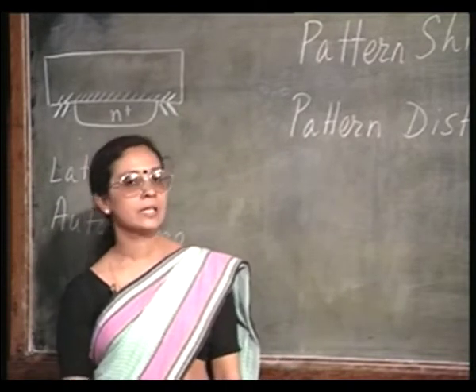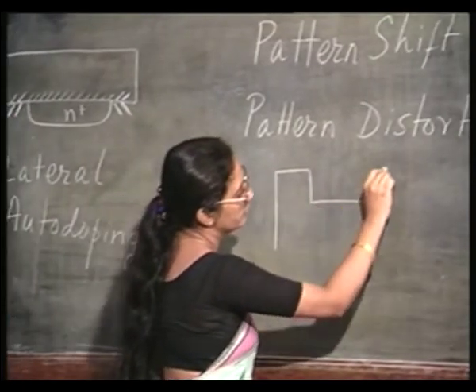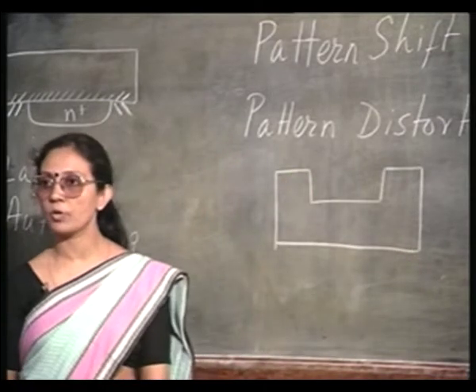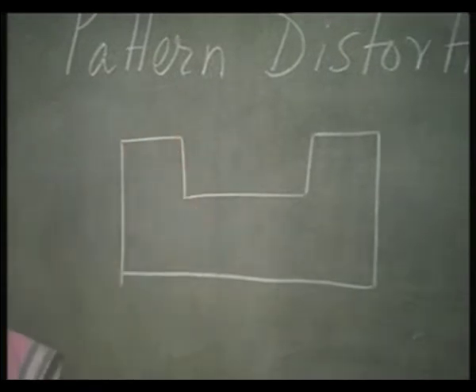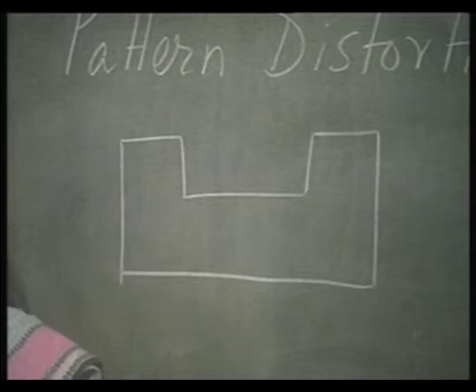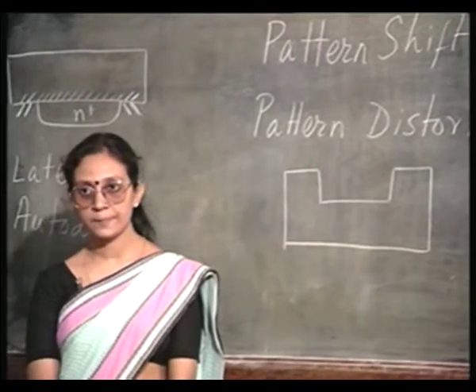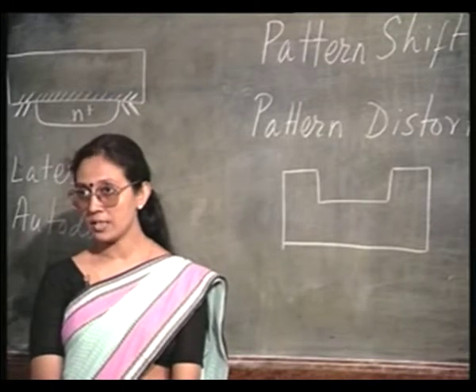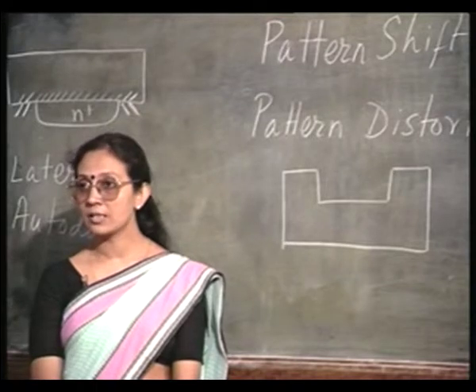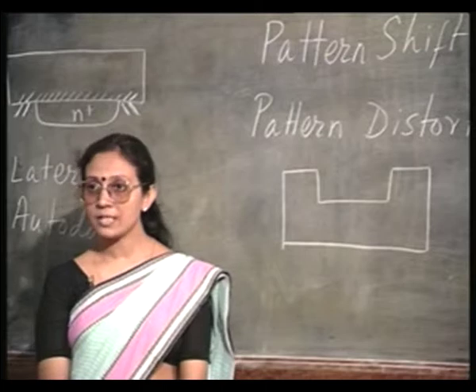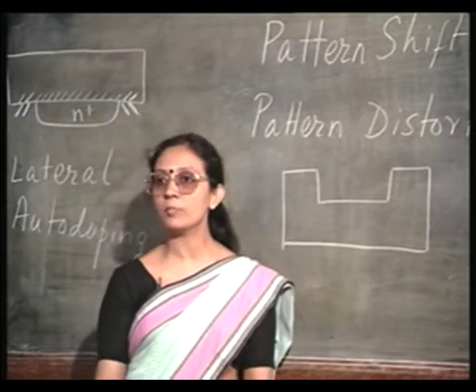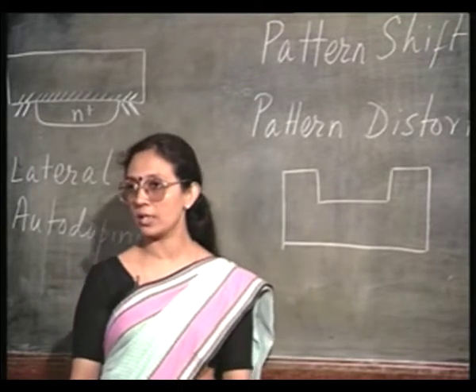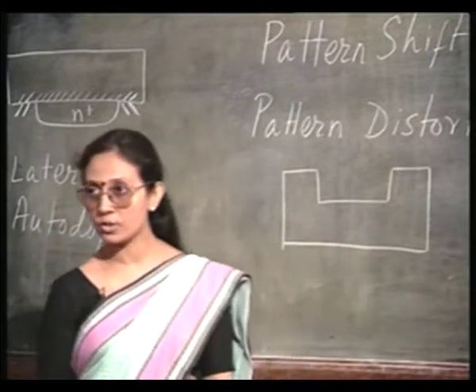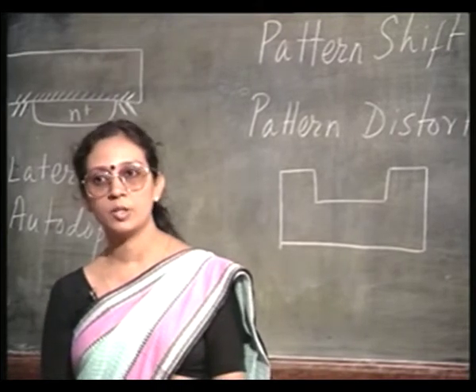Okay. So, whenever there is a step on the surface, you are exposing a number of crystal planes at this step. See, the surface may be 100 or 111 or whatever, but whenever there is a step, a number of crystal planes are going to be exposed. And when epitaxial growth is taking place, it is taking place anisotropically, that is, the growth rate is going to be dependent on the crystal orientation. That is why you do not have uniform growth rate. If you had uniform growth rate, this step will get translated into the epitaxial layer, no problem. But because this growth rate is not isotropic, it is anisotropic, you get all these problems of pattern shifting and